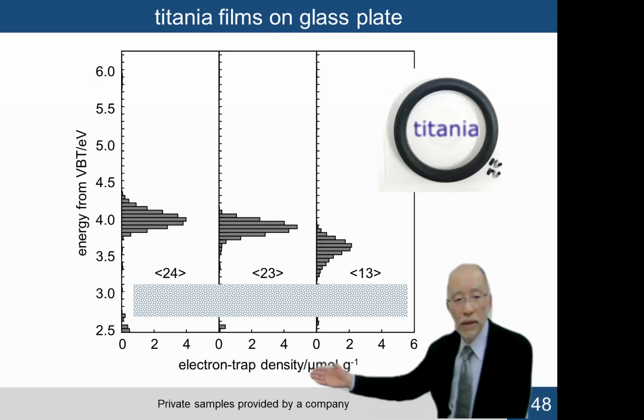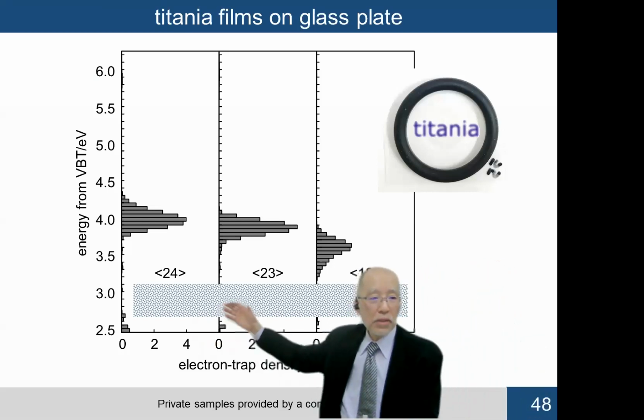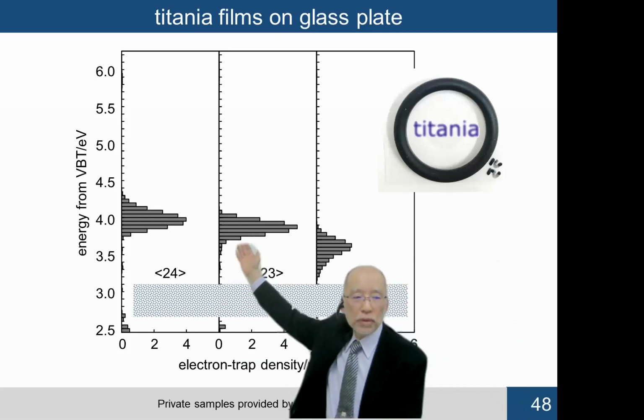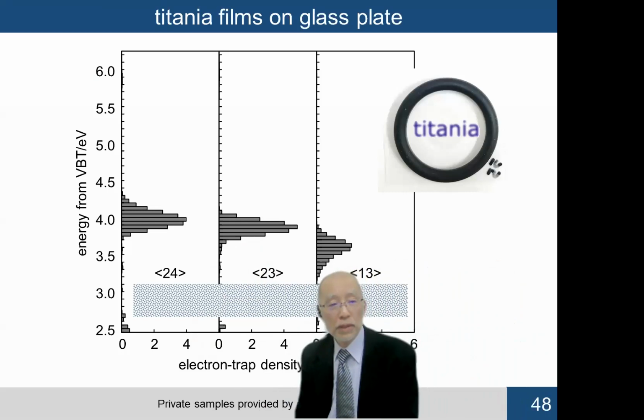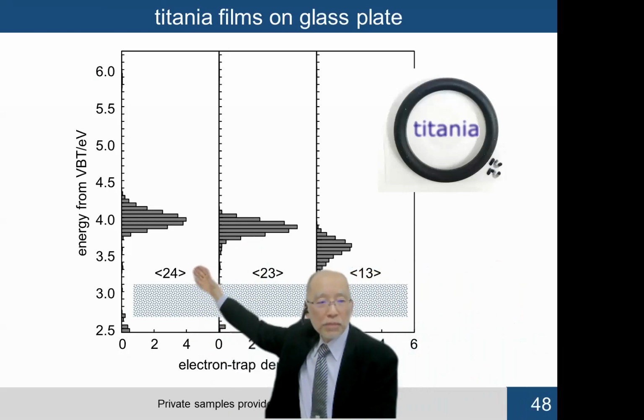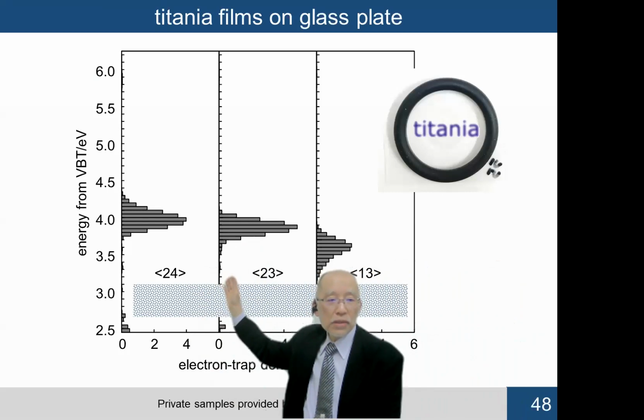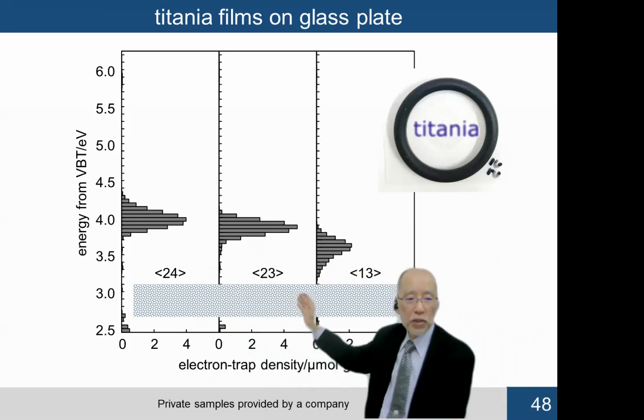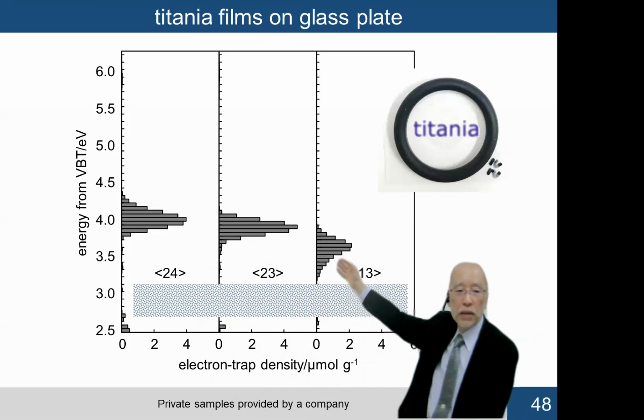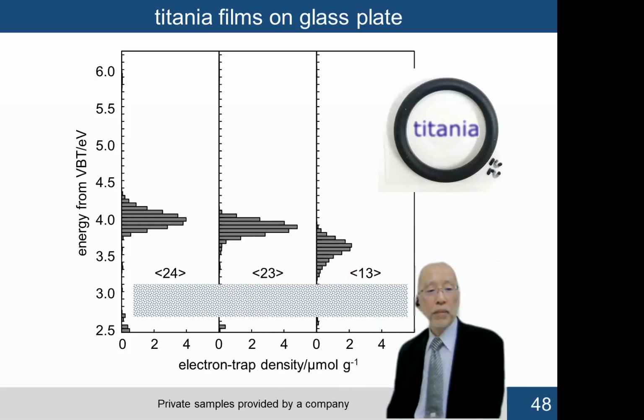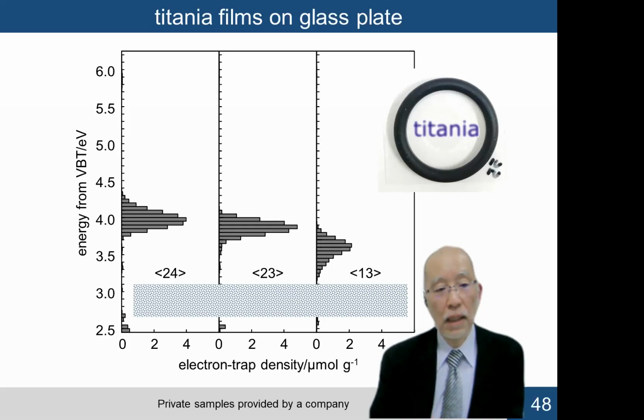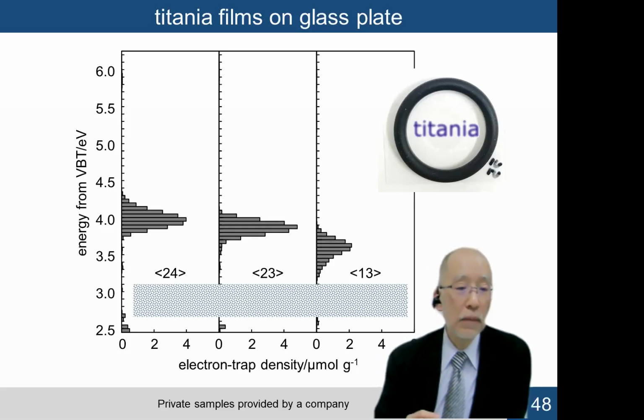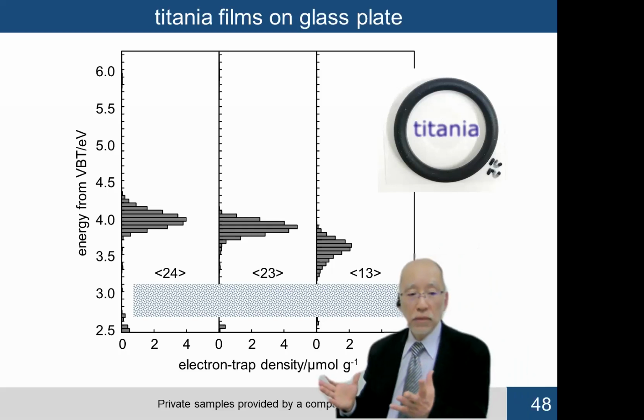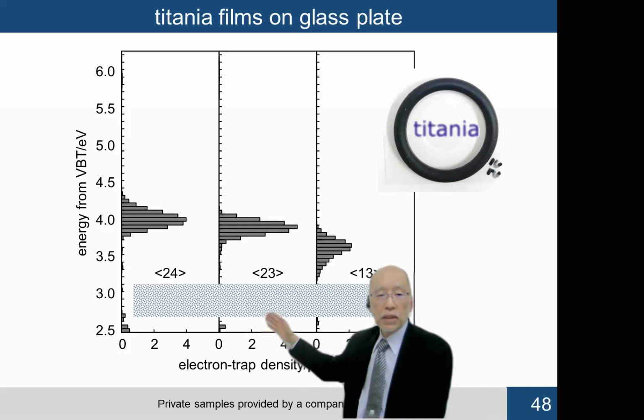But depending on the preparation conditions, the patterns are different. And probably this position, about 4 electron volt, is amorphous titania. The peak position is a bit lowered with this sample, and much more shifted with this sample. Probably this one crystallized a bit compared with those materials. So the other analytical methods don't give any information on the structural difference of those titania films, but this technique tells clearly those materials are different.